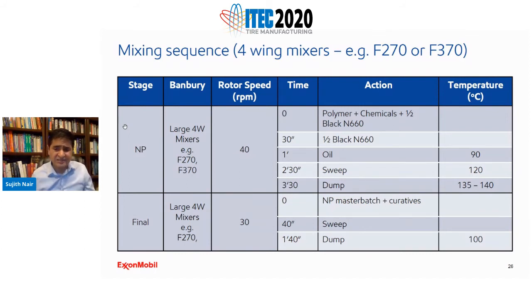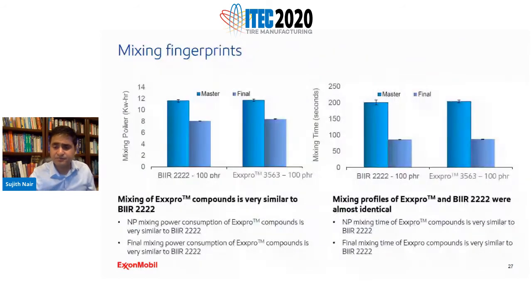But as I said before, Exxpro is extremely resistant to temperature. So we have had customers coming and asking us, can I go higher in temperature? Can I go to 150 or 160? And the answer is yes. With Exxpro, you can go to 150 or 160 or even 170. There's no problem. And we have done this, and we have proven that actually the properties are even much better. So you can definitely go to higher temperatures. In this particular experiment, we have just used this as a standard.